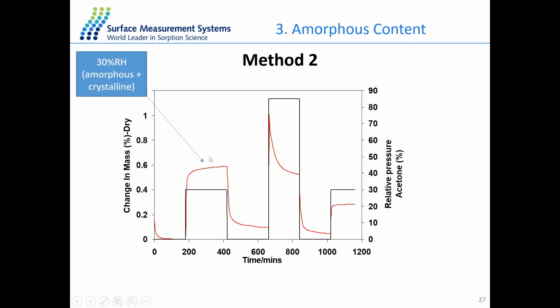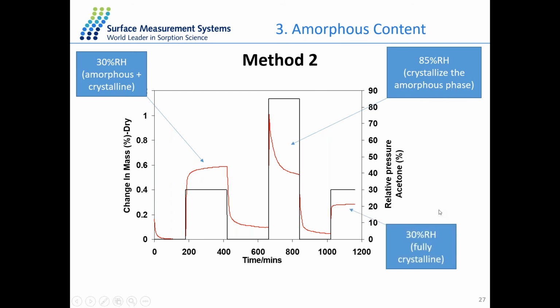So first we expose the sample before the crystallization point, about 30% RH, for both the amorphous and the crystalline material. And then we expose the sample above the crystallization point, so about 85% RH, to crystallize all the amorphous content inside the material. And the third stage, we just expose the sample again to 30% RH, for the fully crystalline material this time.